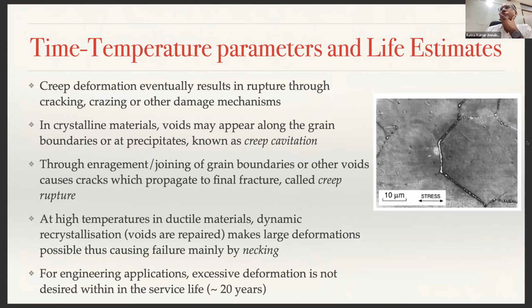So now, how do you estimate life? The time temperature parameters and life estimates. Suppose you have a creep problem. Creep deformation eventually leads to what? Rupture in the material, that means the breaking of the material. Typically in crystalline materials like metals, you may have voids. Here you can see void generation appear along the grain boundaries. The small voids appear along the grain boundaries and precipitates, and this is what we call cavitation. That might eventually lead to the failure of the entire component.